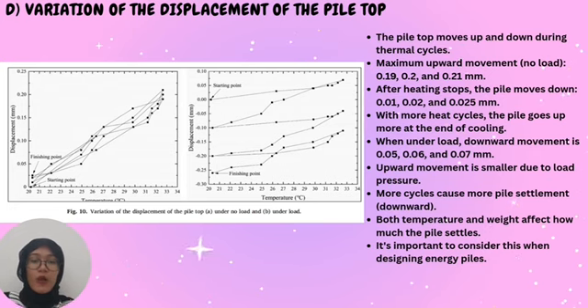On the other hand, when a load is applied, the downward movement becomes more noticeable, reaching around 0.05, 0.06, and 0.07 mm. Here, the upward movement is smaller because the pile is held down by the load pressure. Additionally, more heating and cooling cycles lead to greater settlement of the pile in the downward direction. Both the temperature changes and applied weight significantly affect how much the pile will settle over time. This information is very important to keep in mind when designing energy piles to ensure their long-term performance and safety.